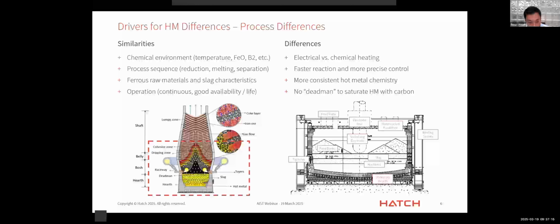The ferrous material typically used is very similar, typically lower grade ferrous burden, like BF grade pellets. And again, that's because both the blast furnace and the ESF are excellent at handling large amounts of slag and very effective at rejecting the gangue and completely metallizing the hot metal. Whereas the DRI process does not reject any gangue and does not completely metallize the ore. Similarly, both the blast furnace and the ESF have a lot of process advantages. They're both continuous operations, have very high availability, and extremely long campaign life as measured in a number of decades.